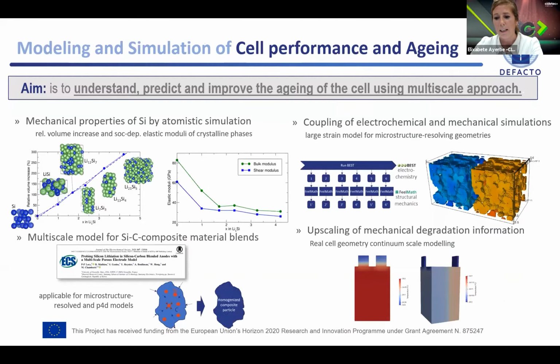Once the electrolyte filling is done, and we assemble the cell after the formation step, we know that with repeated cycles the cells degrade. In particular, in the DEFACTO project, we will be dealing with silicon anodes, where silicon undergoes expansion and contraction phenomena, and this might cause stresses and modify the structure of the electrode, causing premature degradation like delamination, cracking, and so on. So within DEFACTO we will concentrate on the mechanical properties and how mechanical degradation is linked to electrochemical degradation.